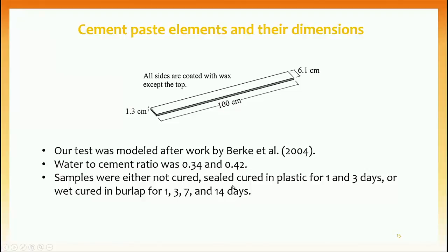So today I'm going to talk about the experiments that we have done at Oklahoma State University, which were showing the impact of increased wet curing. We used very thin, long paste beams, which were coated on all sides except the exposed side, which was under different lengths of wet curing, seal curing, and no curing.